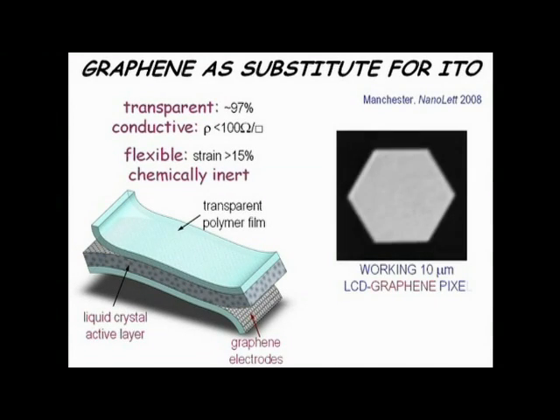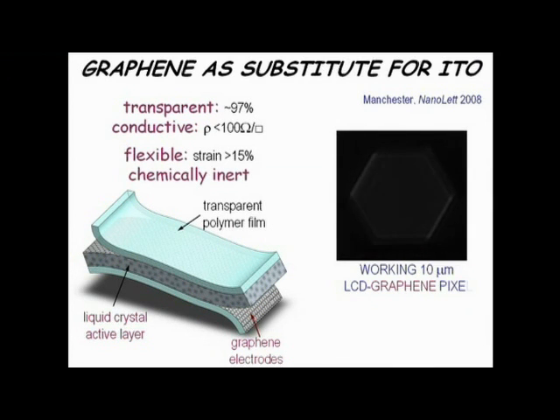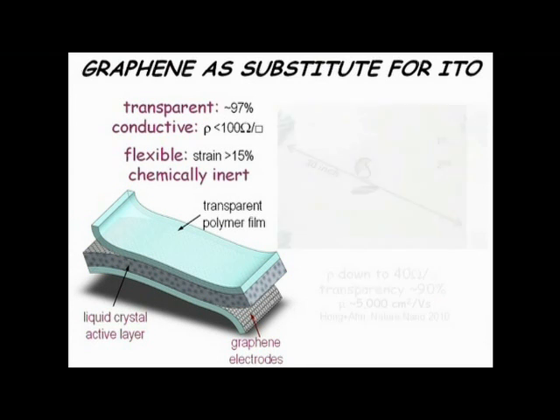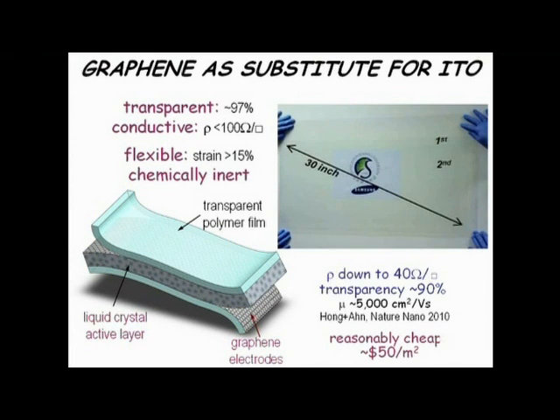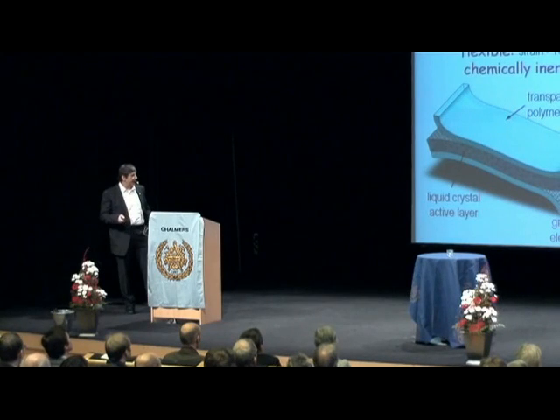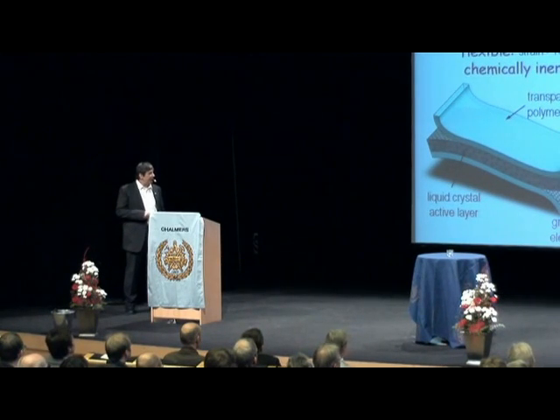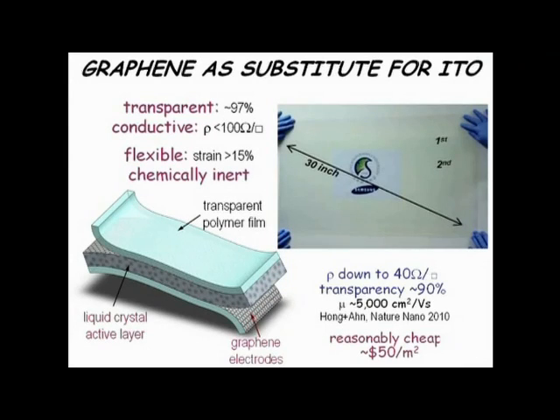So the idea in all those gadgets where currently ITO is used is to use graphene instead. It was a speculation for quite some time, but then it was a working cell, but very small, a few microns, before 2008, before industrial production. But nowadays, people can produce big roll-on production of graphene in industrial quality and at a decent price of $50 per square meter, with very competitive parameters describing conductivity and transparency.